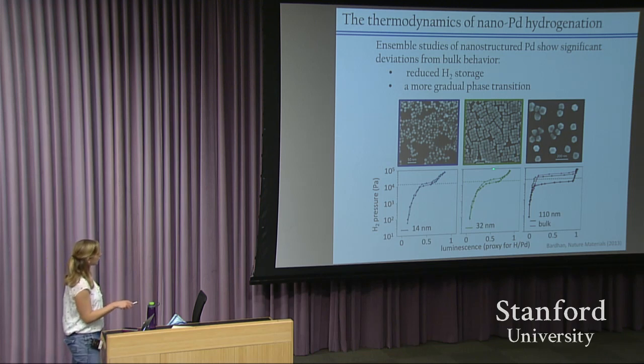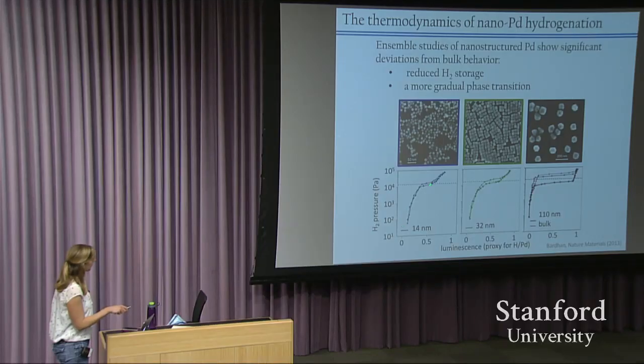And then as they nanostructured the materials, these were all single crystalline nanocubes that had sizes of 32 nanometers. They noticed that these isotherms became more sloped. So you'll notice that for a fixed hydrogen pressure, the amount of hydrogen in the system was less than what they had in the larger nanoparticles and in the bulk system, so hence the reduced hydrogen storage capacity. And then you'll see the gradual phase transition become more pronounced as the nanoparticle size was reduced.